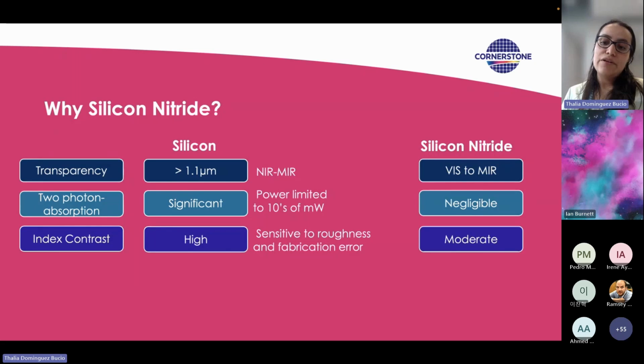When we look at silicon nitride, because it has a moderate refractive index contrast, in this case, it has a refractive index of 2.0 compared to 1.44 of the silicon dioxide, the difference is smaller.